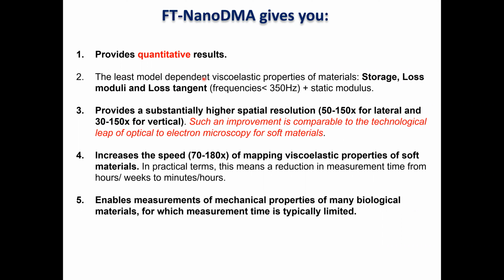So this method is, as I said already, the least model dependent. Viscoelastic properties of the material, storage and loss modulus, and loss tangent can be measured, plus the static modulus. So far, we have developed this mode working up to 350 Hertz. It's simply defined by the resonance frequency of your scanner, so there is no real serious limitation for that. But for soft materials, this is the most interesting behavior, because for higher frequencies, you have a pretty boring monotonic increase.